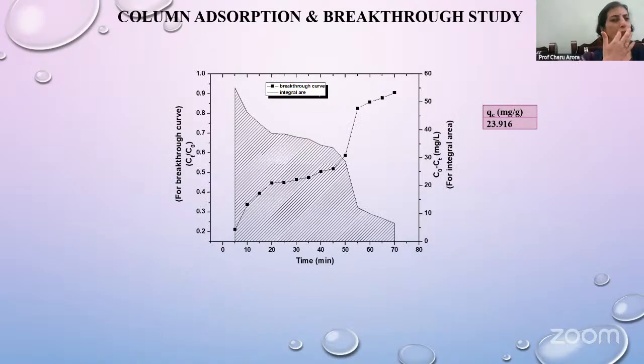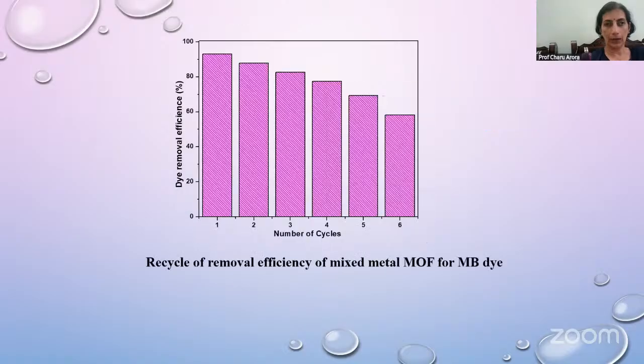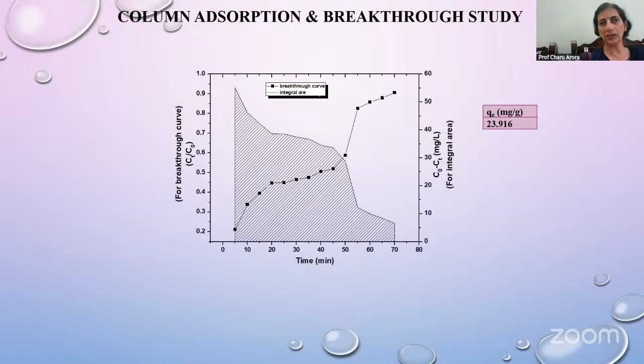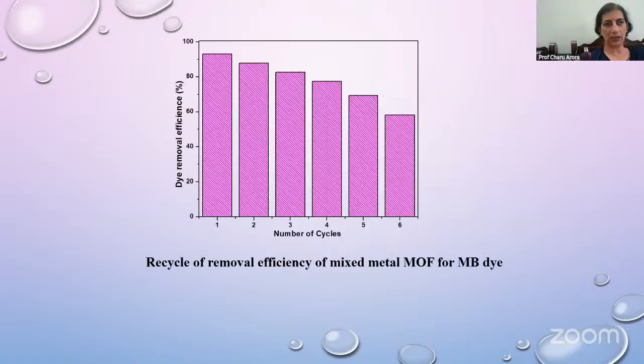This is the column plot showing that good removal takes place and the column was exhausted in 70 minutes. Here, the value of Q is much higher than the previous case. And it was observed to be reusable with more than 50% removal efficiency up to 6 cycles.